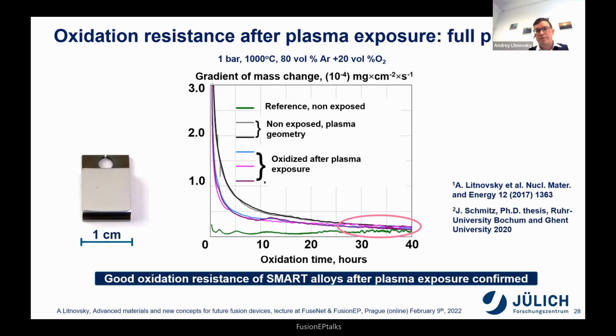Finally, of course, the ultimate test, because we first have regular operation, then, God forbid, but it might happen, the accident will happen. Does the smart alloy which was exposed to the plasma still have enough material to, let's say, suppress the oxidation? The ultimate test was the oxidation resistance after the plasma exposure, to have the full picture.